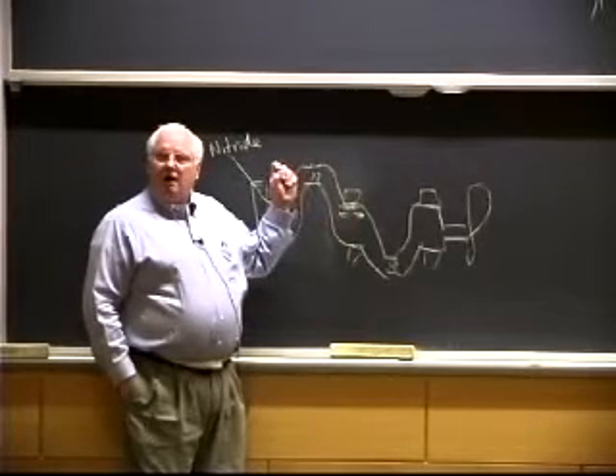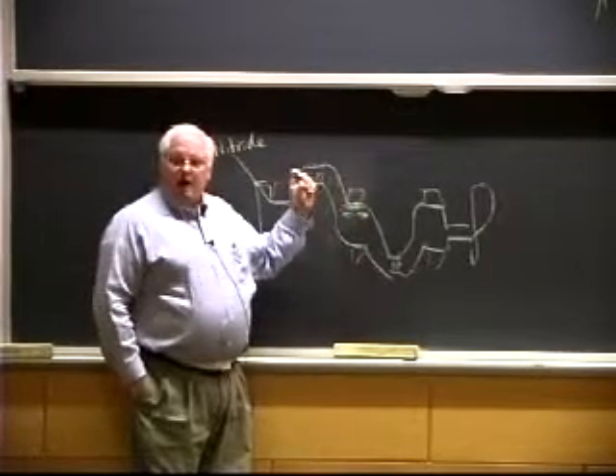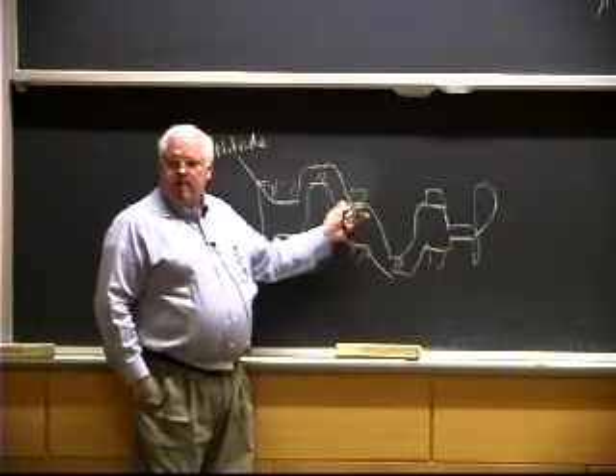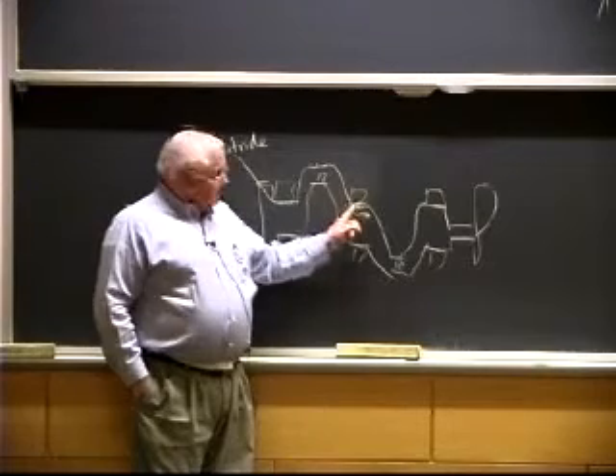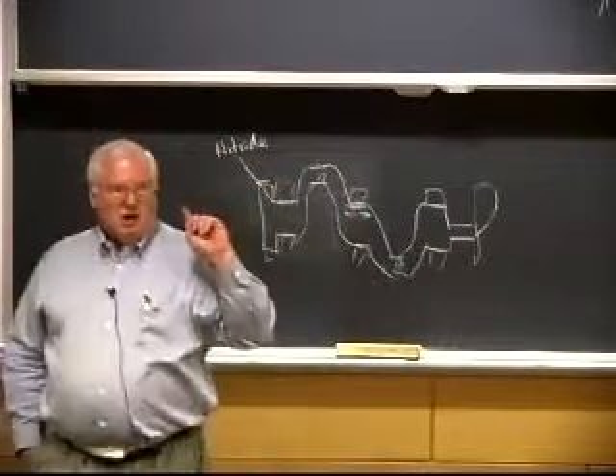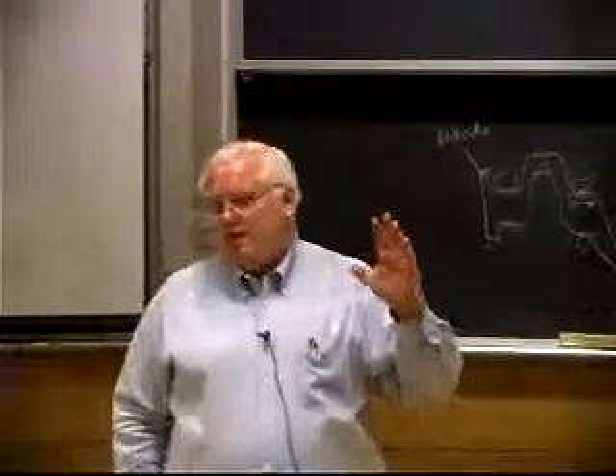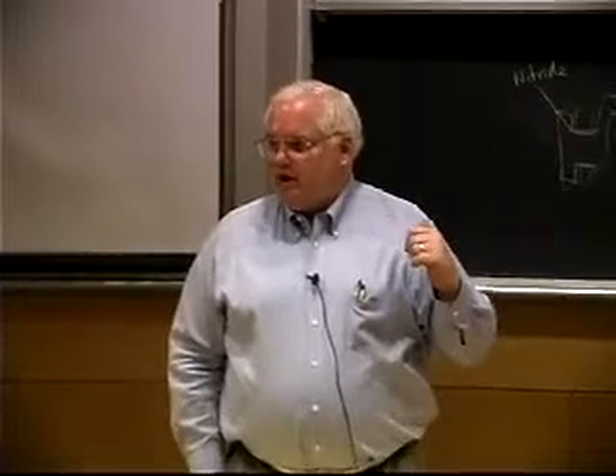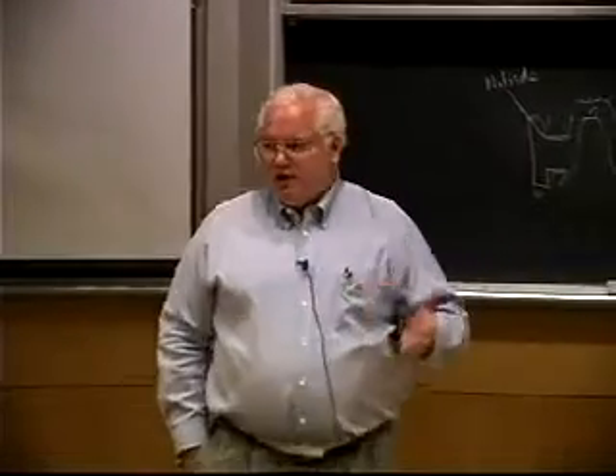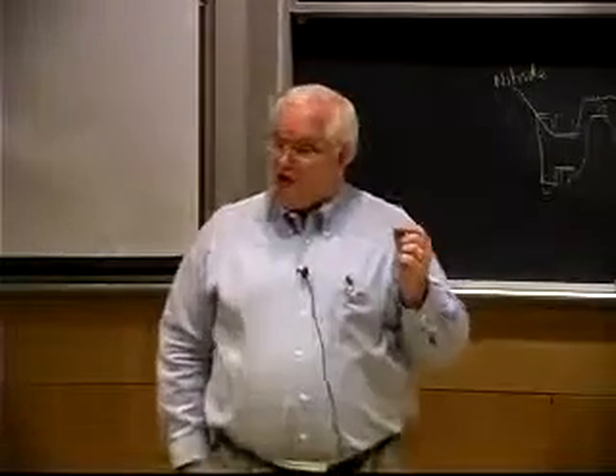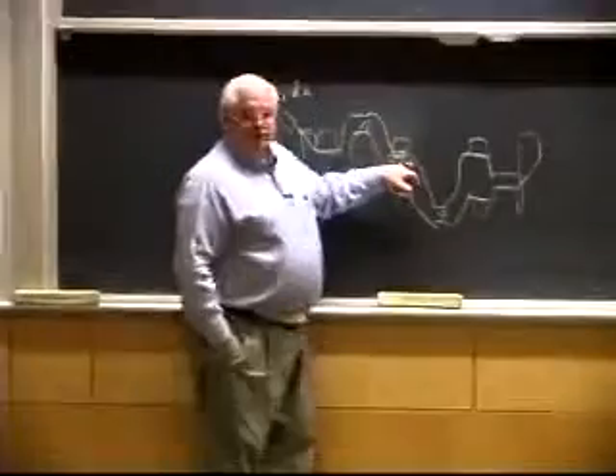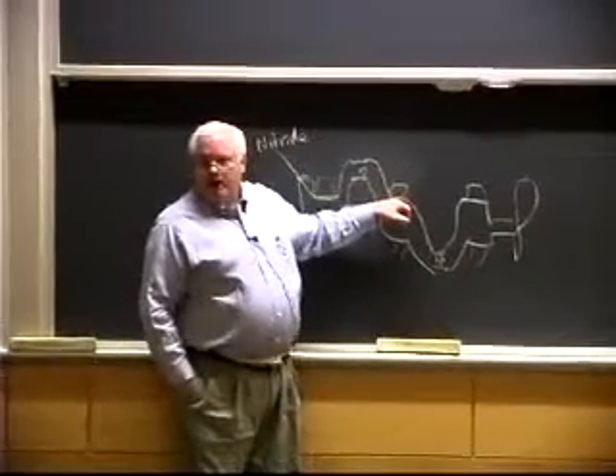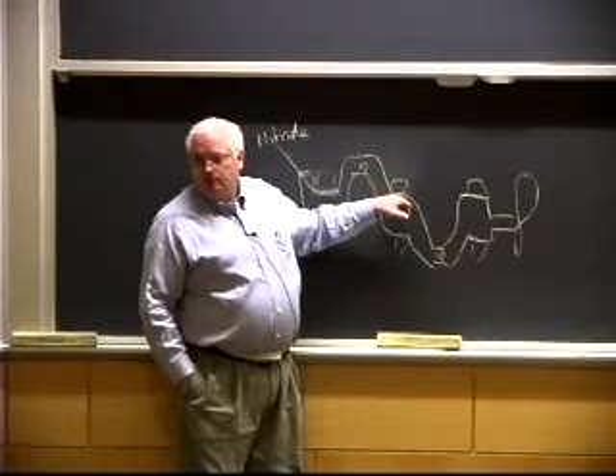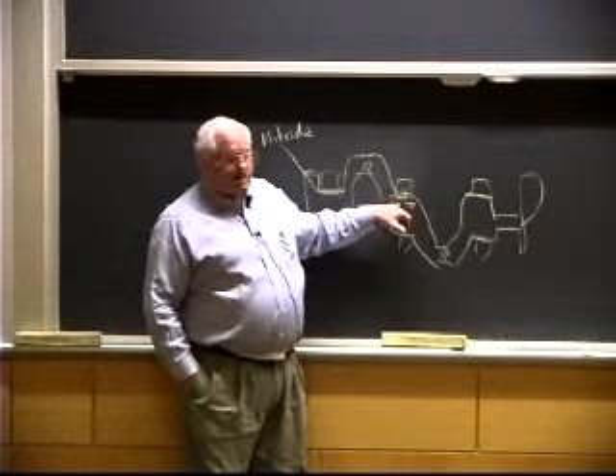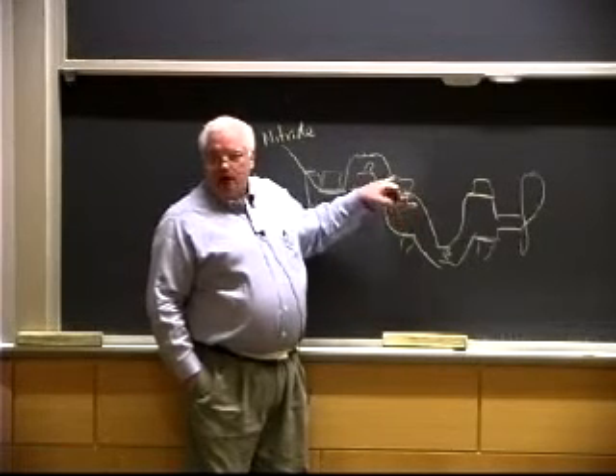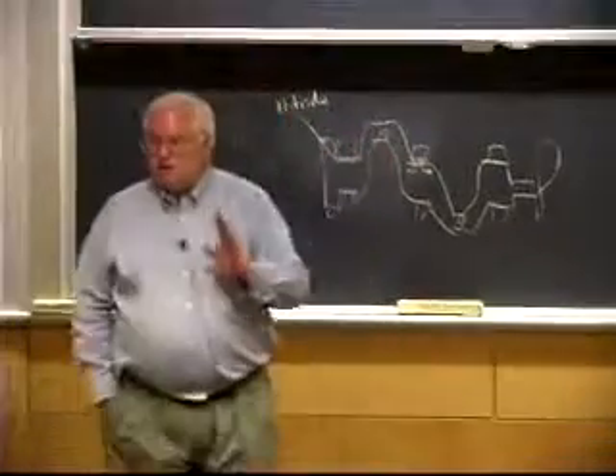And it turns out both of the big engine manufacturers over the last 5 or 10 years have been having tremendous problems with these tensile stresses and some heat treating defects that occur beneath the surface. The fatigue cracks start 2 millimeters beneath the surface. They don't start on the surface because you have a good nitrided case. If you didn't have that nitrided case, you'd have a third less fatigue life on a good crankshaft. But unfortunately, when people forged these crankshafts, they overheated them, and they produced some little flaws on the order of only 100 microns in size. Those flaws, if they're right on the surface, are not harmful because they're in a compressive stress state. But when you add the positive stress state right beneath the surface to the operating stresses, that flaw size gets to be large enough that you get fatigue cracks. And these crankshafts are failing in service.